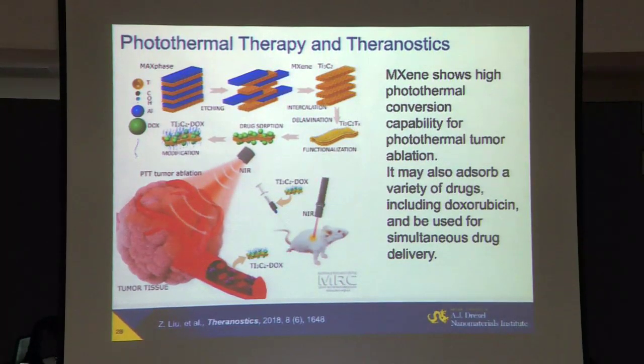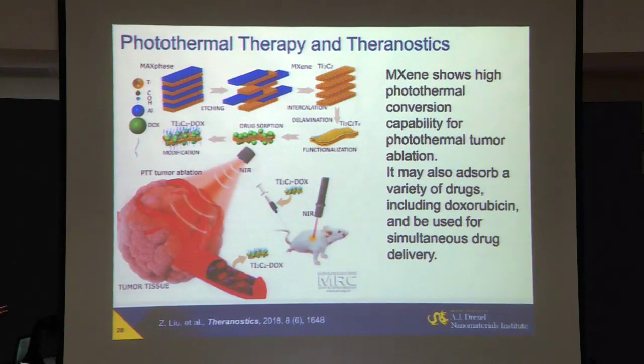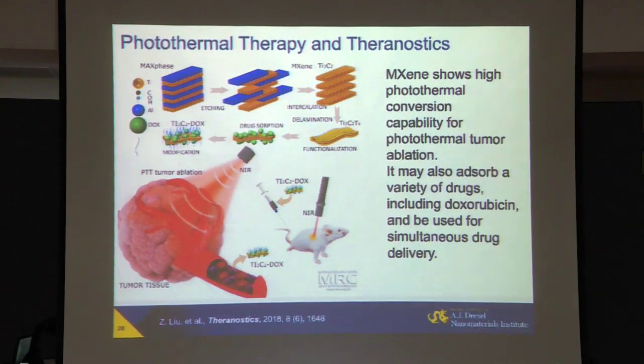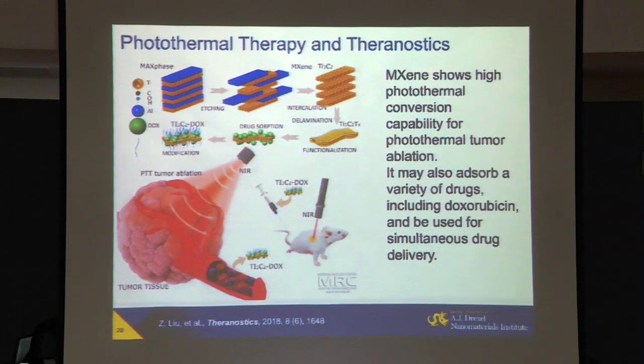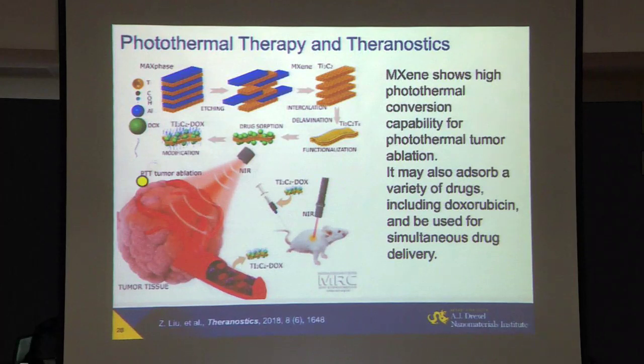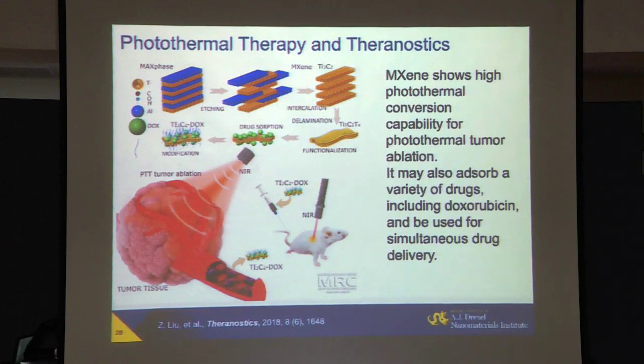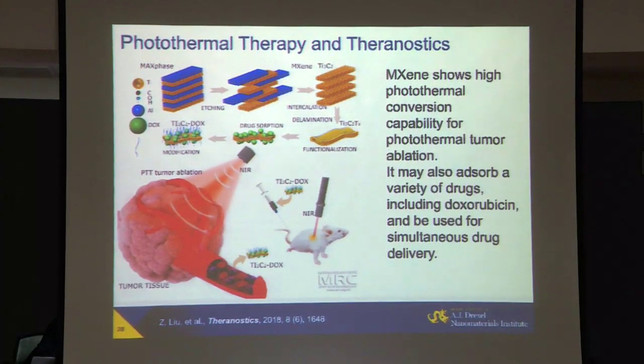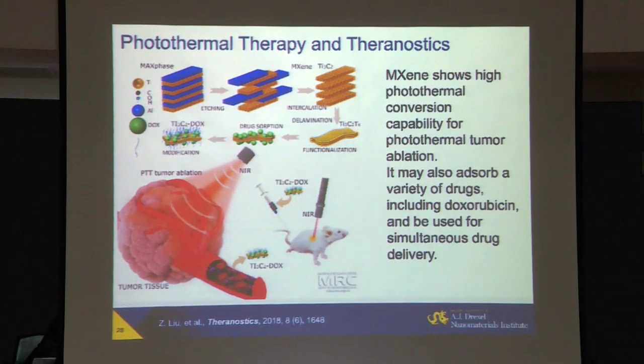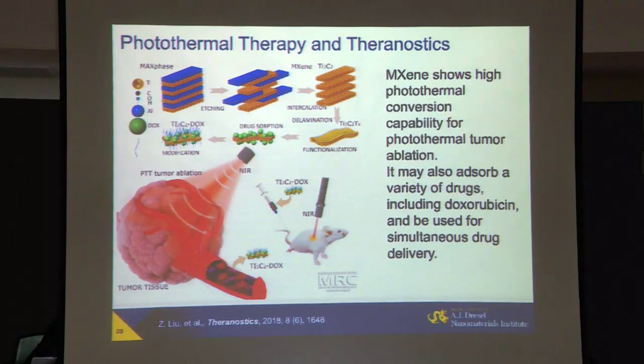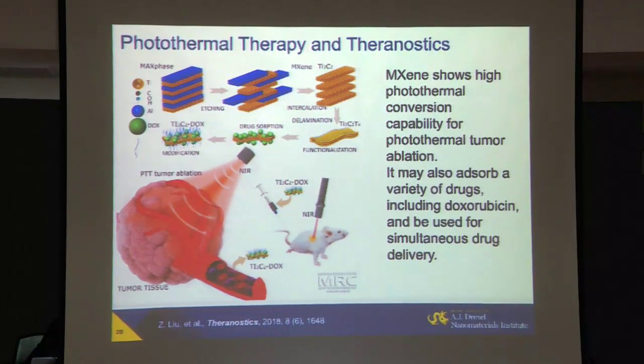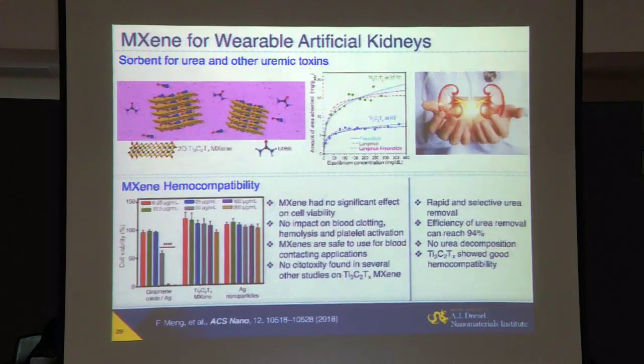I mentioned just a couple of minutes ago that many MXenes have plasmon resonance, so they basically absorb light and transform it into heat in the infrared range. So they can be used as light to heat transforming materials. And a big application they found is photothermal therapy, destroying cancer cells by illuminating them with red light because, for example, titanium carbide Ti3C2 has plasmon resonance at 780 nanometers. This is exactly the position for a red diode laser. So it's a very, very common one, and it can go much, much deeper into tissue compared to visible light, which had to be used, for example, with gold nanoparticles. Moreover, many MXenes have plasmon resonance much, much further into the infrared, so infrared radiation can be used to heat it here.